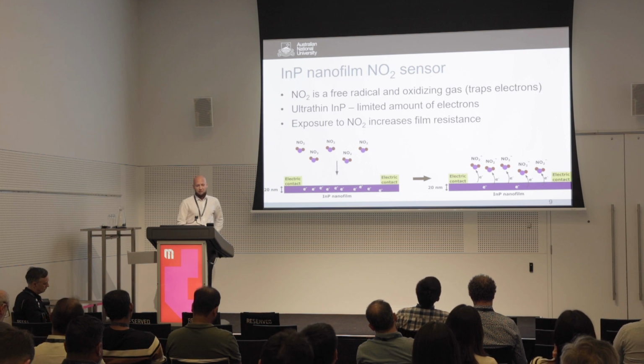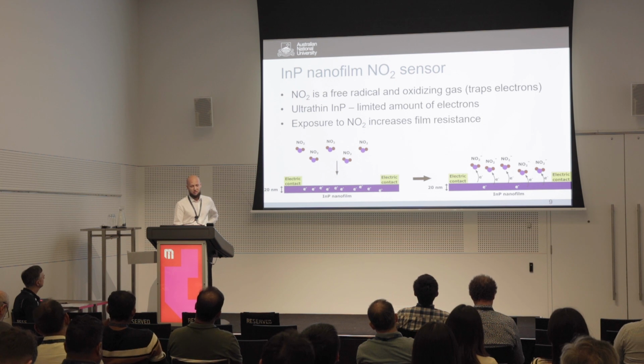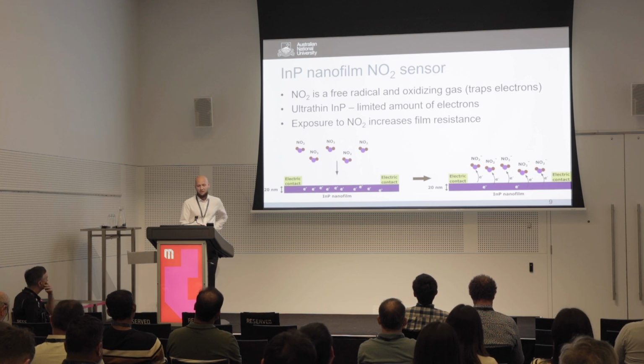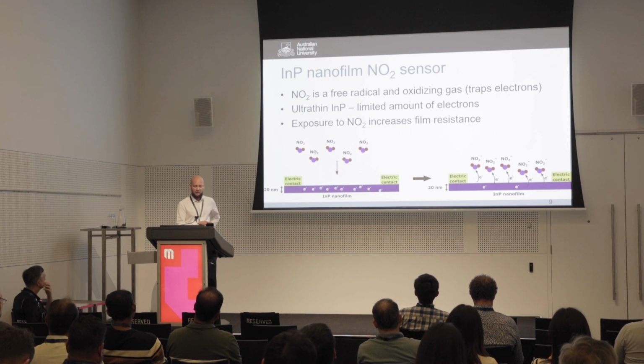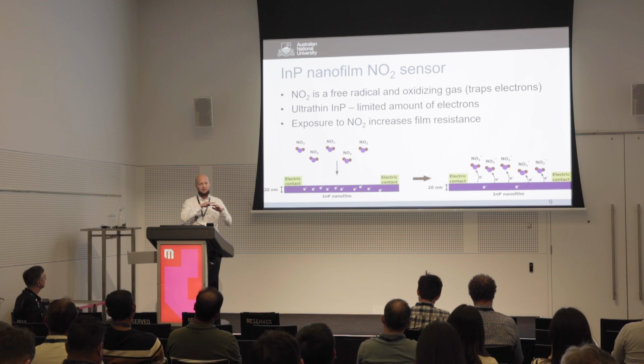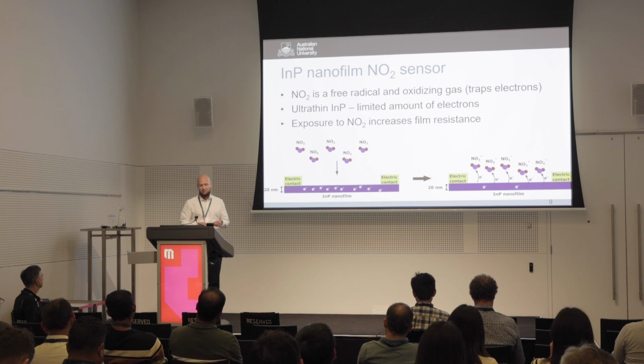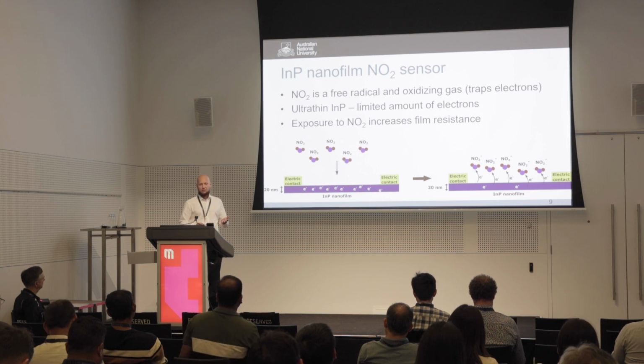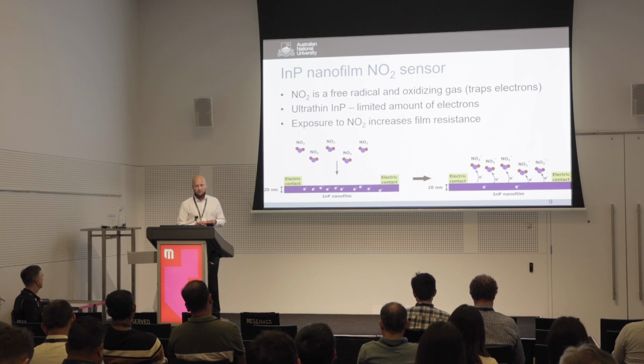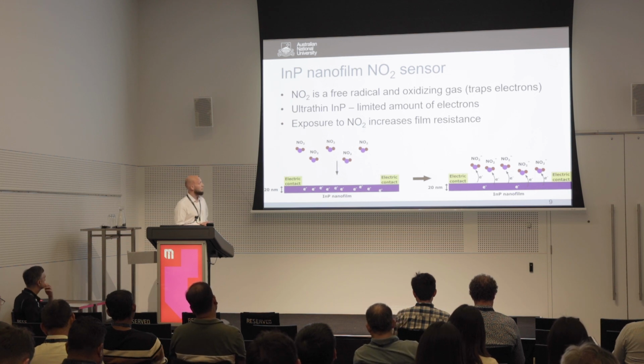So we made a NO2 sensor from indium phosphide nanofilm, and the operational principle is such that NO2, it's a free radical and an oxidizing gas, meaning that it traps electrons. And when we have this ultra-thin indium phosphide film, in the whole thickness of the films, there's just so many electrons that can conduct current. So when it reacts with the NO2, that can have a significant effect on the resistance.